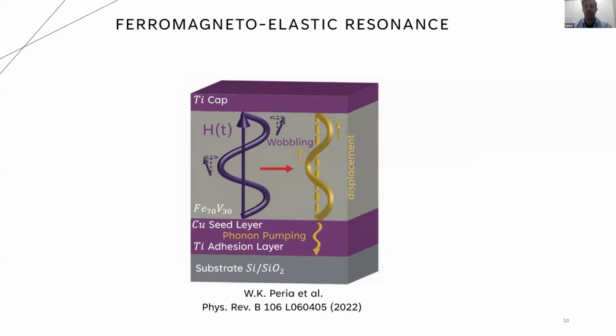But what is going on here physically? Let's start from the beginning. In our FMR experiments, we said that the microwaves can create a wobble in the spin. The quantum of this magnetic wave is called magnons. But at the same time, our film can also host mechanical vibrations, which, as we mentioned, are called phonons. The packet of energy of this mechanical wave is the phonon. But the question here is how these two separate systems interact and talk to each other. The answer is that they are linked by magneto-elastic coupling.